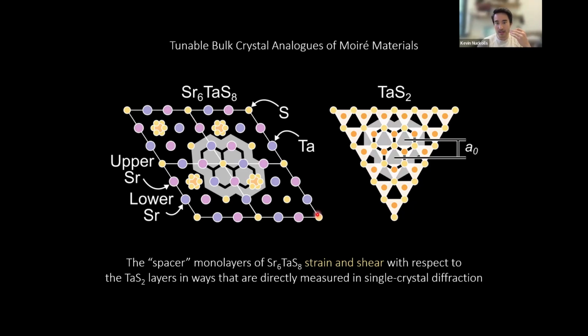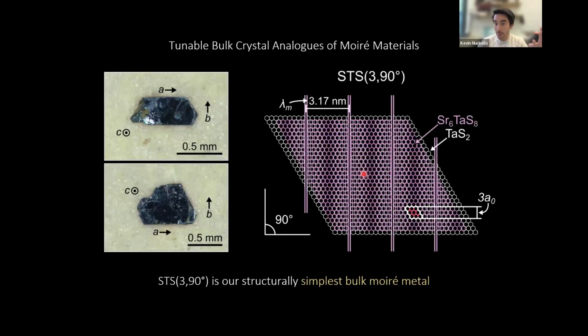To really visualize that, I think that we have a simplified diagram where we can display this hexagonal lattice of tantalum disulfide as a perfect hexagon, and we can depict this monoclinic lattice first as a perfect hexagon, then we will strain and shear it into its monoclinic symmetries, so you can see it's a bit skewed. And we'll try to layer these on top of one another using all of the diffraction patterns that we quantitatively extracted through our measurements. So in doing so, we can understand the coupling between these layers, and you'll see that one of our compounds, STS(3, 90°), is our structurally simplest Moiré metal. So you can see it's perfectly atomically commensurate in the vertical B-axis, but in the A-axis, it's very simple. It just has a long wavelength, 3.2 nanometer modulation, the Moiré superlattice.